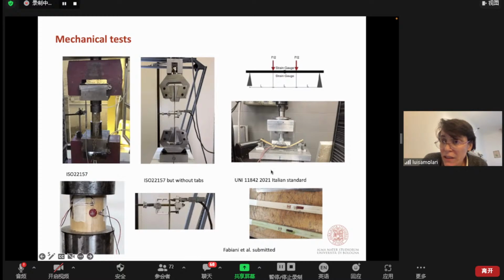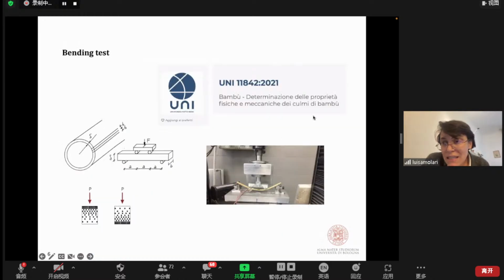For the bending test, we followed the new Italian standard, that is the UNI 11842. And for the measure of the deformation, we put a strain gauge in two directions for the compression, an extensometer for the tension, and a strain gauge in the bottom part of the specimen for the bending test. The bending test, as I already said, follows the new Italian standard, and actually we did the test only on the specimens with the external part on the bottom, because we wanted to test if the surface treatment was doing something or not.